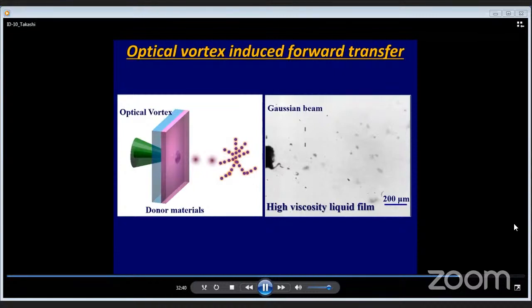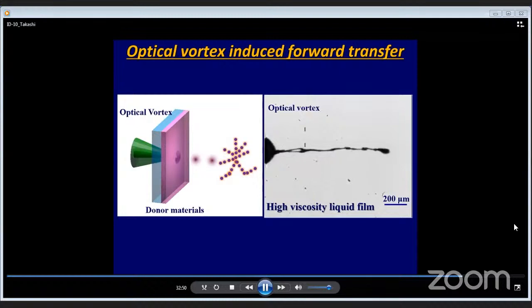Instead of the Gaussian beam, we use a Laguerre-Gaussian mode. At that moment, the Laguerre-Gaussian mode, quite interesting, can create a blister and create a jet. This jet is spinning. Quite interesting. Finally, through the Rayleigh-Plateau instability, this jet ejects a single droplet. The volume of the single droplet is about a picoliter.